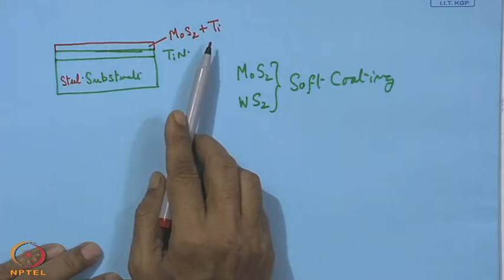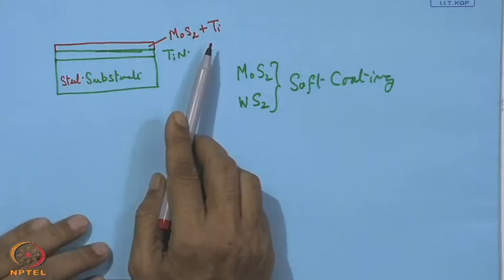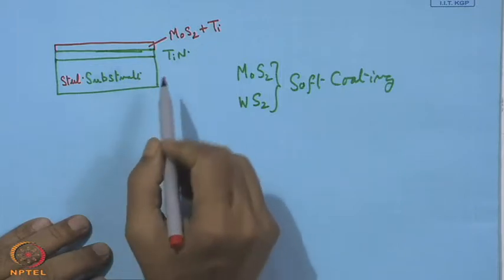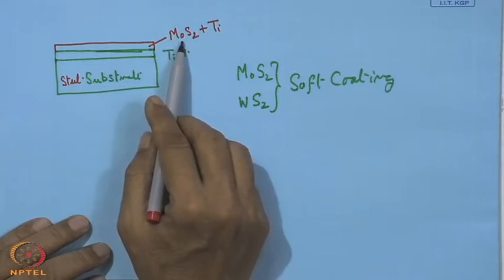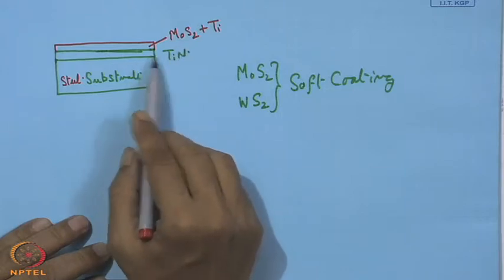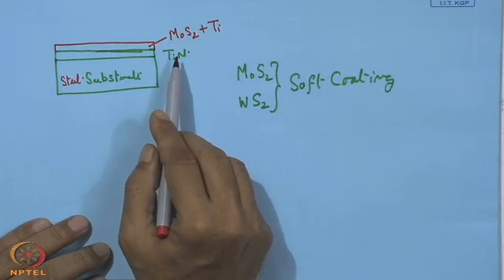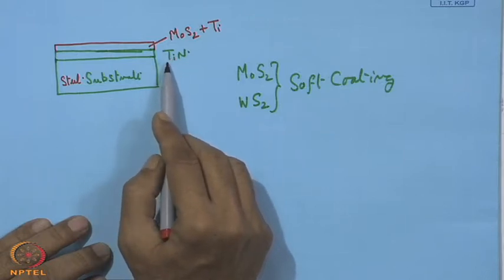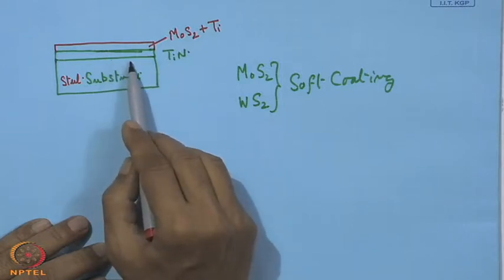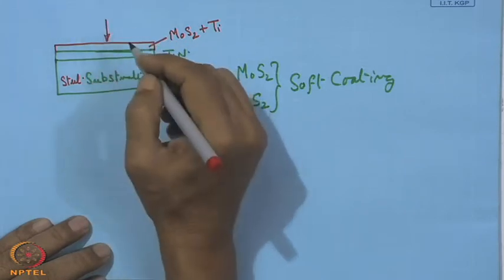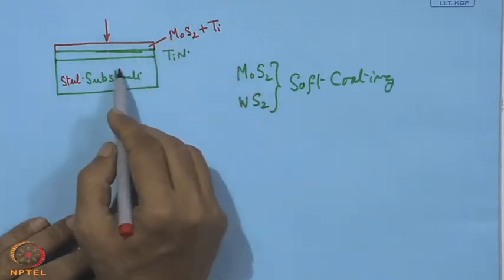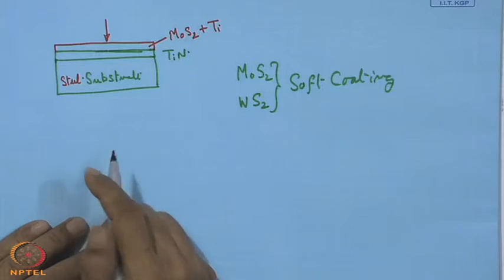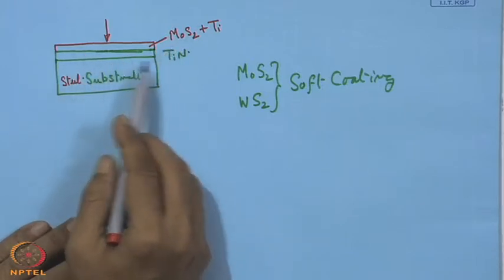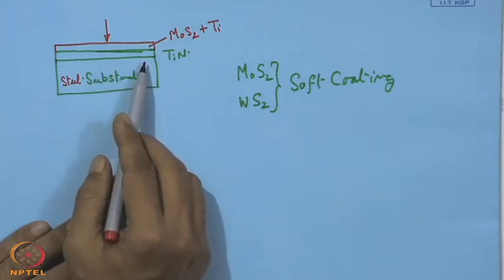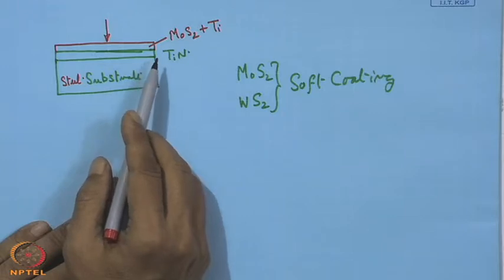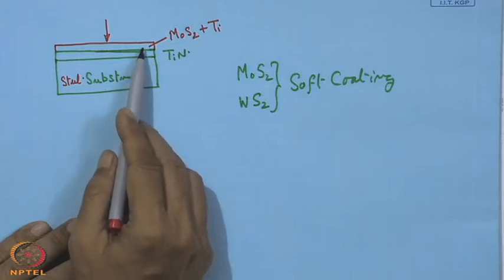So, this way one can also design the architecture of the coating just to improve the performance, and here it is said that the load bearing capability of this coating is better and higher when it is put over a hard coating. So, a soft coating is well supported, well borne by one hard coating, and here the resistance to deformation is more, because when the load is applied on this side, there will be a tendency of deformation. Since this substrate is of lower hardness, so naturally the whole thing will get deformed along with MoS2. But if we have a properly chosen architecture of a hard layer, hard metal like TiN, then it is expected that this coating will improve its performance.